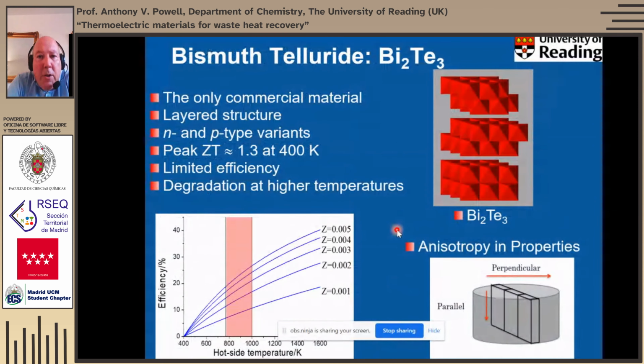The only current commercial material is this one, which is bismuth telluride. This is a layered structure, so it's these blocks of octahedra, like the metal dichalcogenide structure, but taking pairs of them which share common faces. So we have these paired blocks, then a van der Waals gap, and then another block of bismuth telluride. So it's a layered structure.